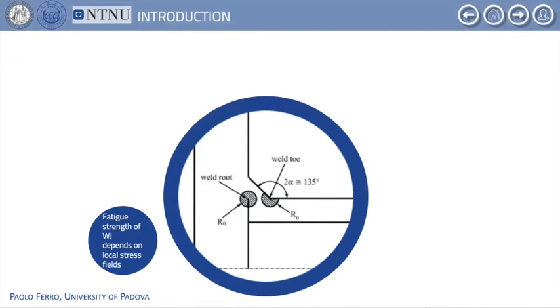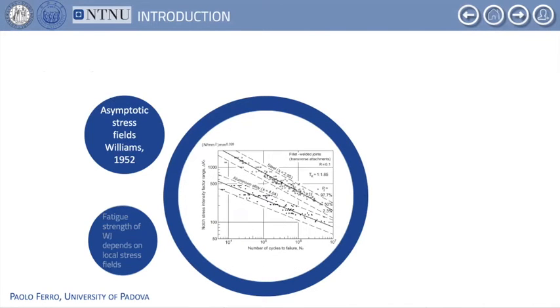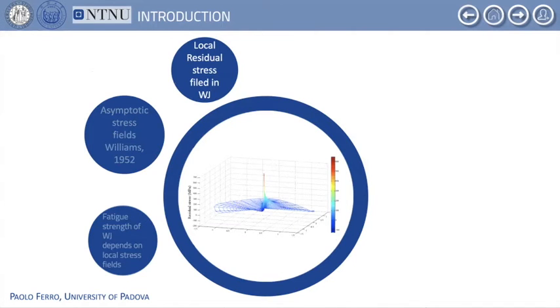It is well known that the fatigue strength of welded joints depends on the local stress field that arises at the weld toe or weld root. Because of such geometrical discontinuities, the local stress fields are singular in their nature, and this is the same thing when we are dealing with residual stress as well.